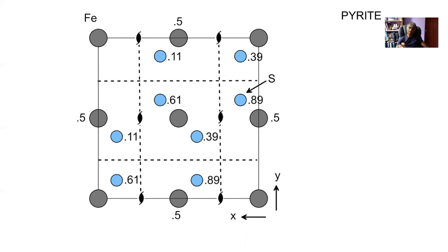So there are only really two symmetry elements in this crystal structure needed in order to describe the translational symmetry elements. There are symmetry elements other than these. For example, there is a center of symmetry at half, half, half. And of course, because we have that center of symmetry, that makes the triads inversion triads, as we discussed in a previous lecture. Three becomes three bar if you have a center of symmetry. So we write the space group as P for primitive, a glide, and bar three.